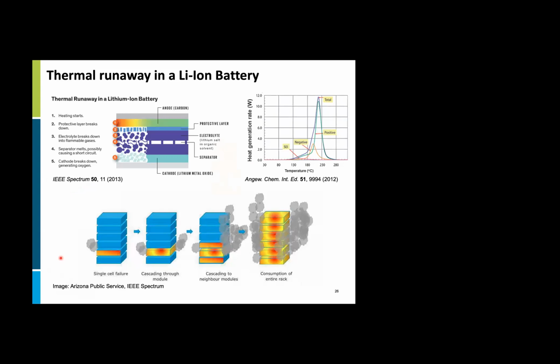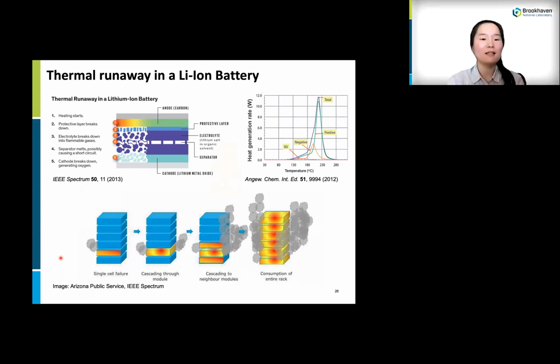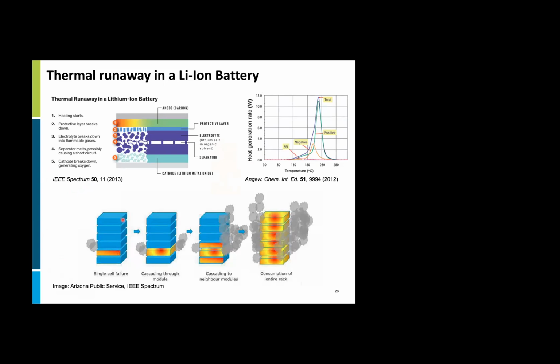So heat-related safety concerns of batteries are strongly related with thermal runaway. It starts with the composition of the surface of the anode, then anode materials, electrolyte and separator, and finally cathode materials become degraded. The important thing is, from the thermal degradation of cathode materials, huge heat is generated, and also, as I mentioned before, oxygen gas is released from the cathodes. So thermal stability of cathode materials should be studied very carefully.